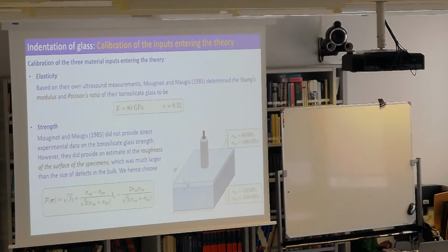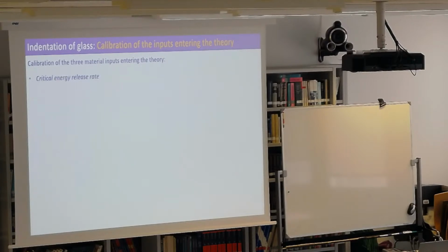You need to calibrate with macroscopic data. We use this, okay, and see what happens. And actually, you will see that it doesn't really matter what we use because of something I'm going to tell you. So Drucker-Prager, heterogeneous on the surface, this value of tensile strength and a large value of compressive strength, this value of tensile strength in the bulk. So, okay, that's our strength.